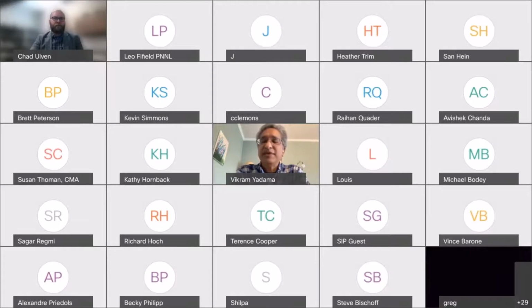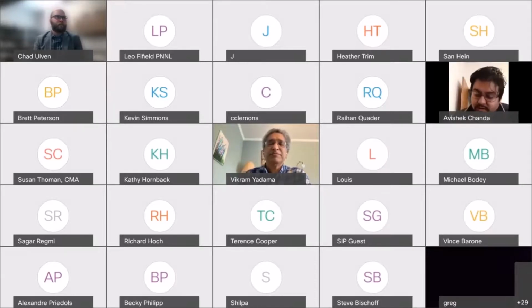We have plenty of time if others would like to ask questions. Chad, just going back to Vikram's question, if we were using alternate layers of carbon and flax, what was the fiber direction of the layers? Were you using unidirectional or bidirectional? The study I showed was unidirectional. And again, you get such a mismatch of stress from one layer to the next when they're not commingled, and that's what breaks down the composite, or dictates the performance very quickly: that mismatch when load goes from one fiber layer to the next. And so in that particular study, yes, we did unidirectional and alternating layers.